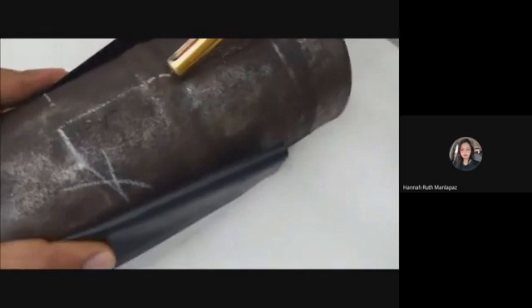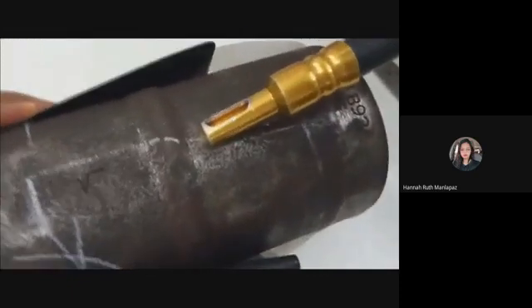Choose the appropriate IQI type according to the sample thickness of the same material as that of the specimen. IQI should be placed in a proper manner on specimen, i.e. source side and wires across the weld. Place letter F, which means film side. Because the other technique is source side, wrap the films around the welded pipe. Place the source at an angle of 10 degrees far of the cap of the weld as you see, to take the film from inside. Calculate the exposure time by application. Process the films inside the darkroom.